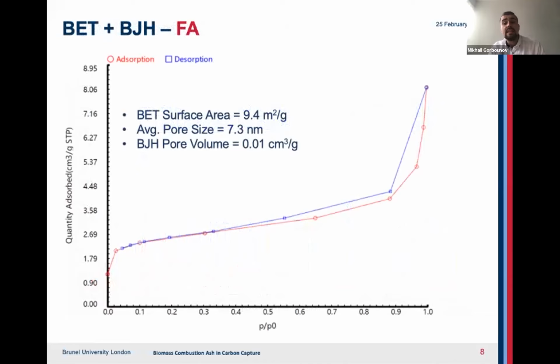Additionally, we have conducted a BET and BJH analysis, and the typical BET surface area of ashes is believed to be in the region of 2 to 6 square meters per gram, with the coal ashes tending to have a smaller surface area in comparison to BCAs. However, the investigated fly ash appears to be much more porous than others reported in the literature. The specific surface area of our fly ash is approximately 9.4 square meters per gram.